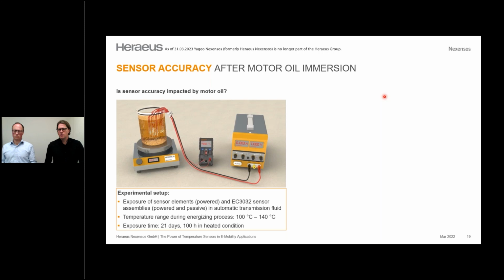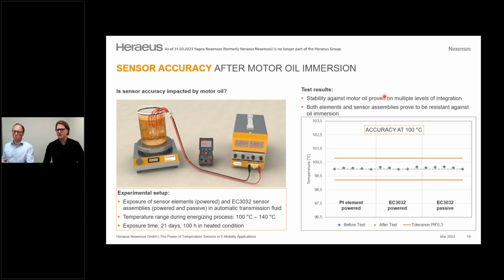In sum, we heated up the complete situation 100 hours and cooled it down over the night, as is usual in the typical use case, because the car is typically in the garage in the evening. In the end, you see on the right side the test result, the results before test and after test. You cannot really see a difference, because there is no change in between.